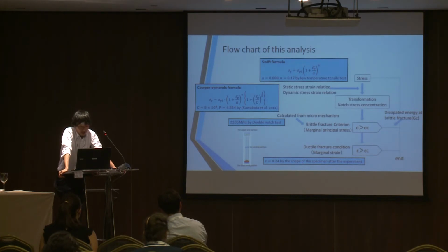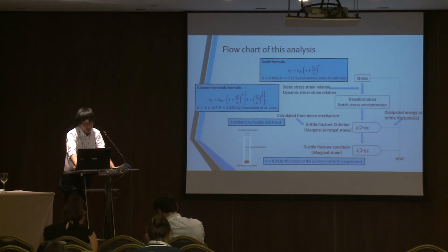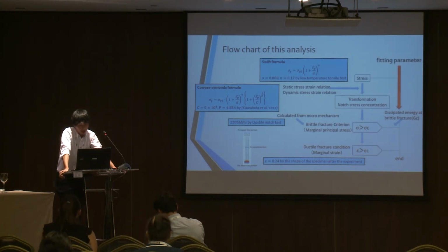If the critical strain is increased, more strain will be accumulated before fracture and the deformation of the specimen will be greater. Using the ratio of the length of the upper or lower end portion of the test piece and the length of the central portion after the experiment, the critical strain was specified. The dissipated energy, GC, can be utilized as a fitting parameter.